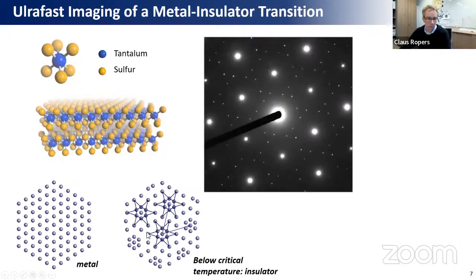So how does this show up in the electron microscope? If we transmit a parallel electron beam through this material, we see this diffraction pattern with a 6-fold symmetry, basically composed of bright and dark diffraction peaks, where the bright diffraction peaks correspond to diffraction from the host lattice. So essentially, those are also present in the undistorted metallic state. And the superstructure formed by the long-range periodic lattice distortion leads to these subtle, much weaker superstructure diffraction peaks in between the main lattice peaks.